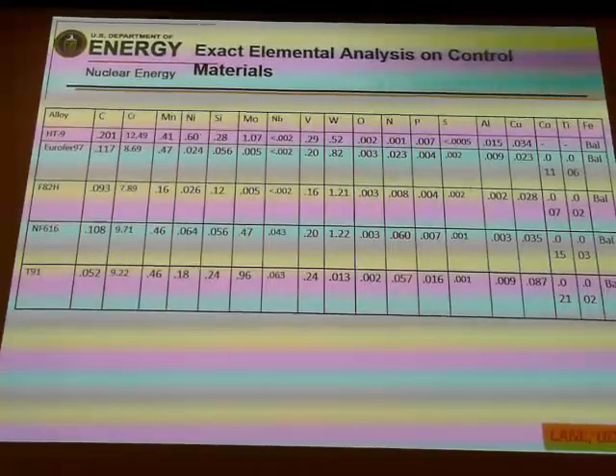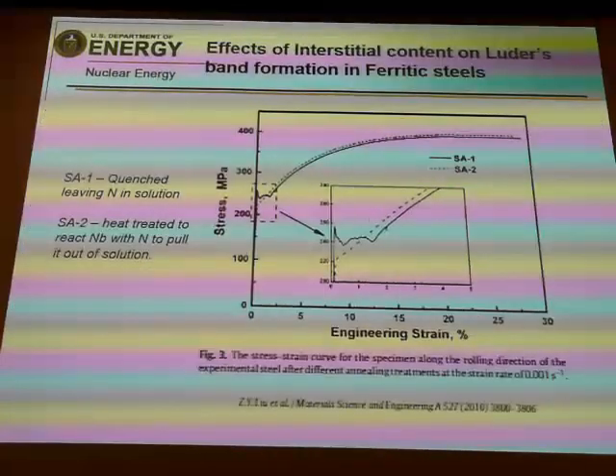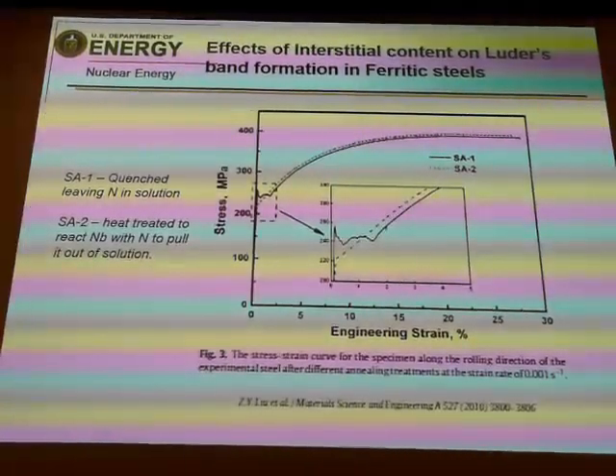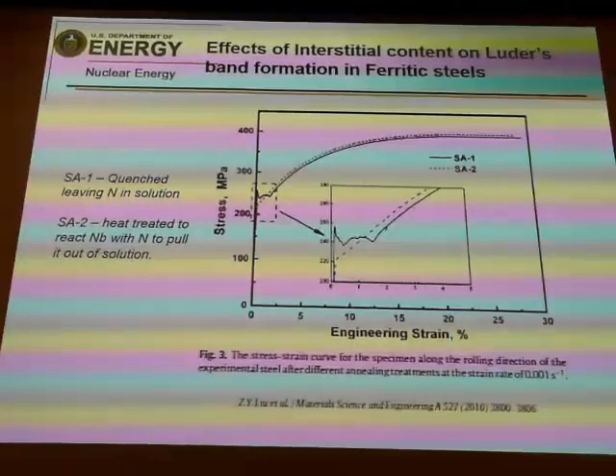And mainly what we're looking at is, can we control the nitrogen content? Other than looking at all the other differences, this is the main difference that we could see between this material and the other materials, the nitrogen content. And why do you think that we centered on that? Well, there's actually a lot of work on interstitial content in ferritic steels.